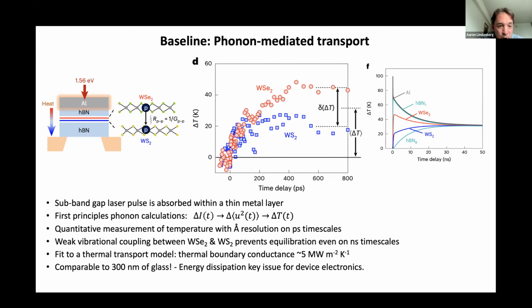These are consistent with other, more indirect measurements of these types of thermal transport processes. And it really is quite an amazingly low number for the conductance, or a high number for the resistivity. Essentially, the effective conductance across this 2D layer, this atomic junction, is comparable to what you would get from 300 nanometers of a typical glass, which is already known as a very poor thermal conductor. So these are the origins of why energy dissipation is such an important issue for these types of systems.